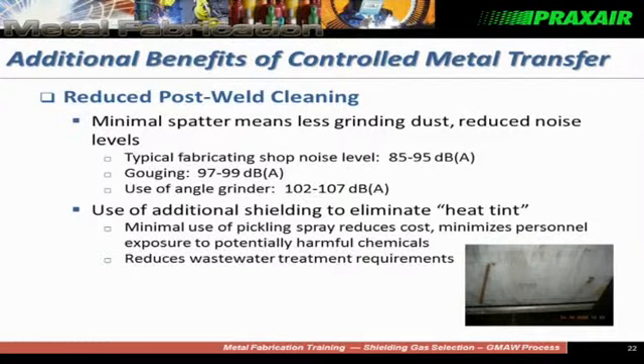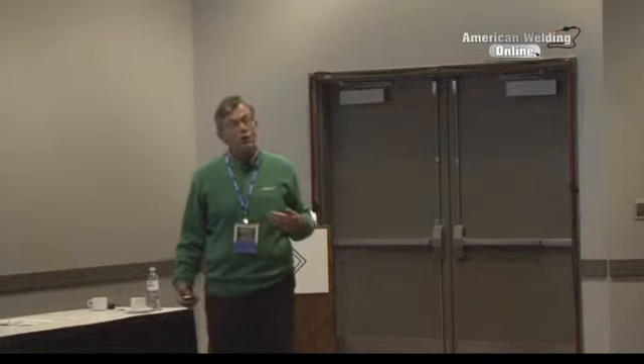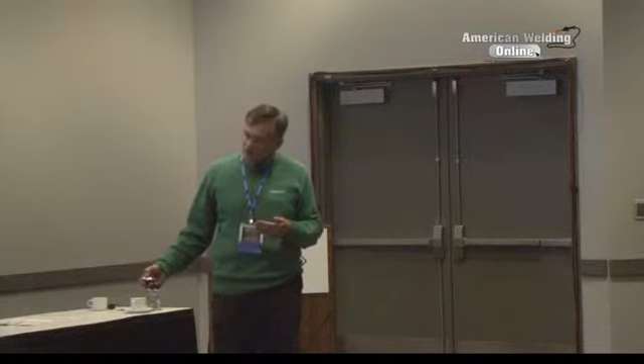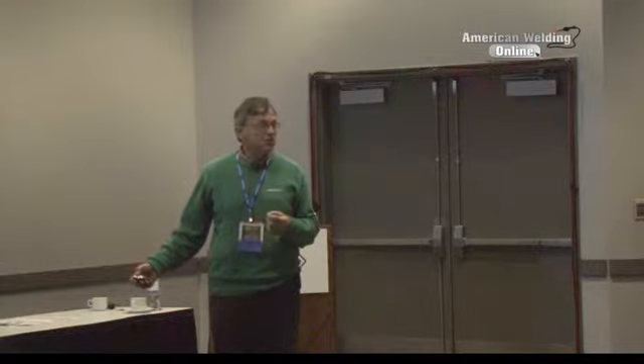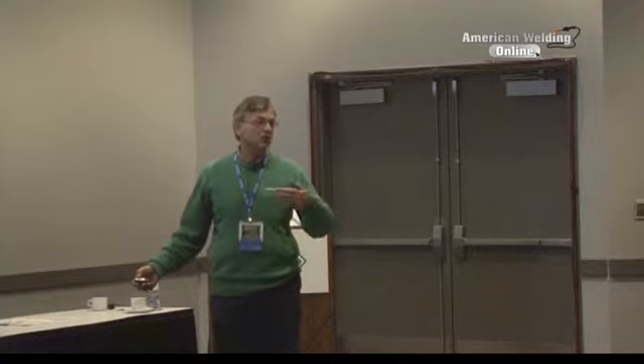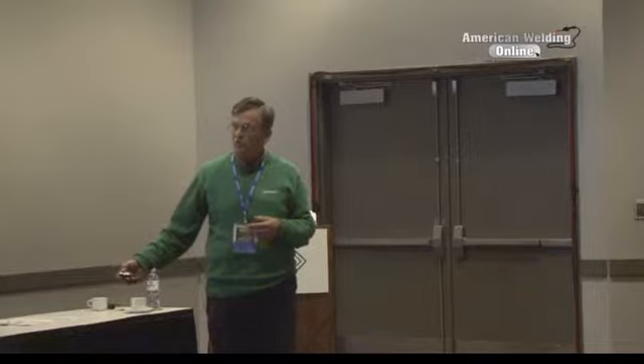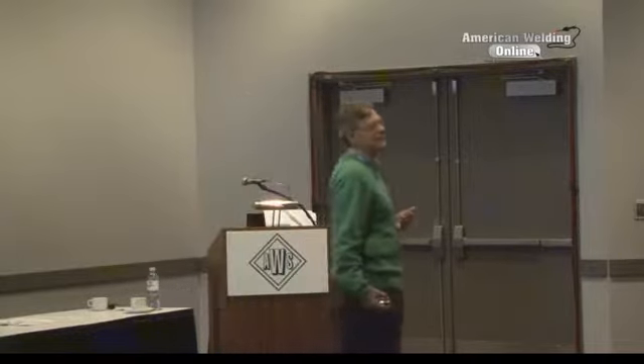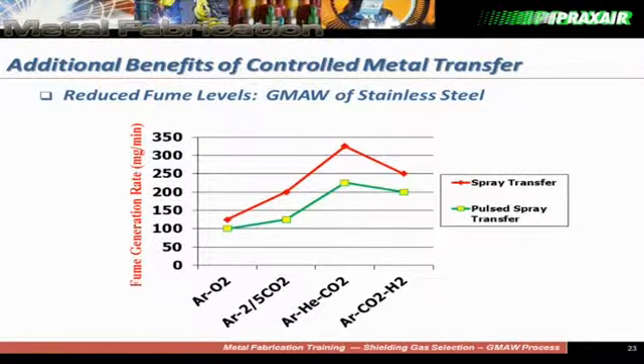Because they would get this heat tinted surface, they had to use pickling chemicals to remove the oxide to improve the appearance. As a result of using those chemicals, they were having a disposal issue with EPA because of disposal of these chemicals. So they were looking for an alternative way to avoid use of chemicals. And so actually over here, it's not perfect, but this was done with just using some nitrogen on the back side of the weld through a little diffuser to just shield that back side of the weld. And as a result, even though the shielding wasn't on when the arc first started, it essentially eliminated that heat tint surface. So, again, another way to look at optimization to eliminate the use of some of these chemicals.